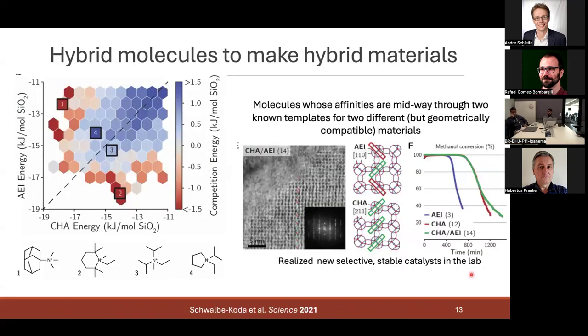And one of, I think, the coolest examples is that we were able to find molecules that were halfway good for two different zeolites. So in this example, right, this is the molecule from before. This is a total success to make this chabazite zeolite. This is the binding energy. So this would be a really, really strong directing agent to direct towards chabazite. And this second molecule is a very good directing agent for AEI, a different zeolite. Right, this is why you have such a strong binding energy.